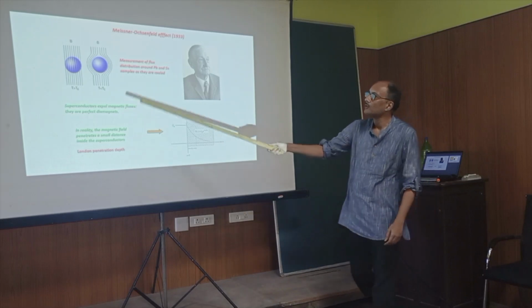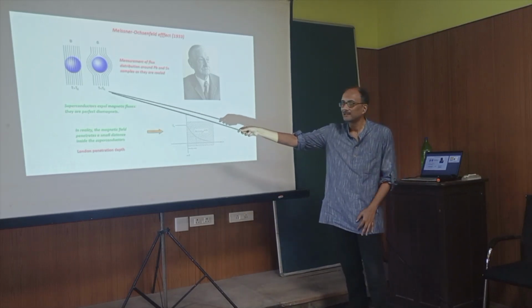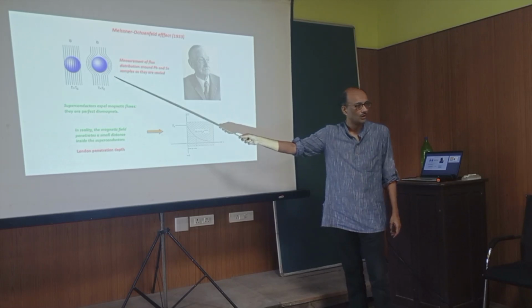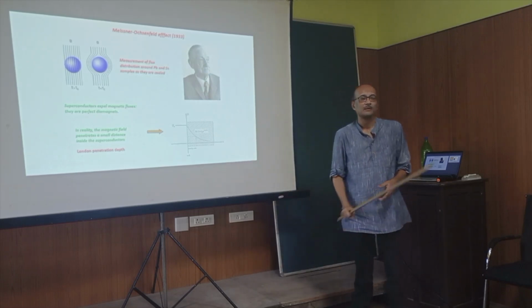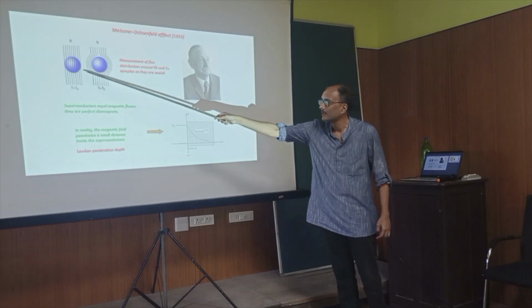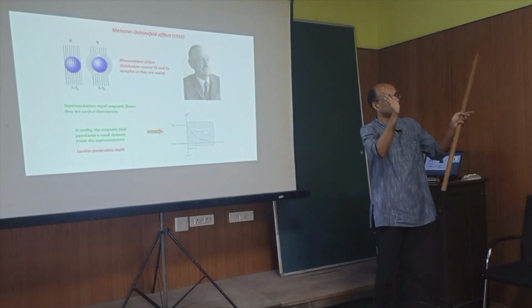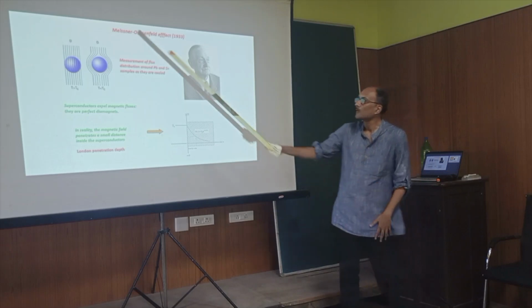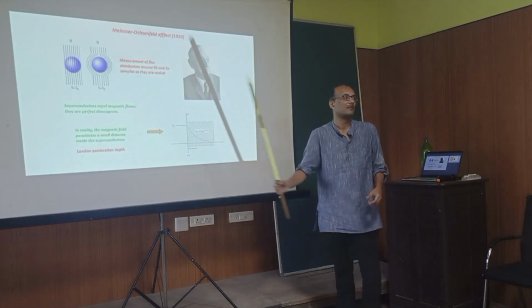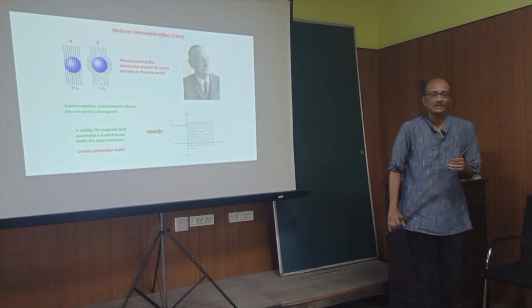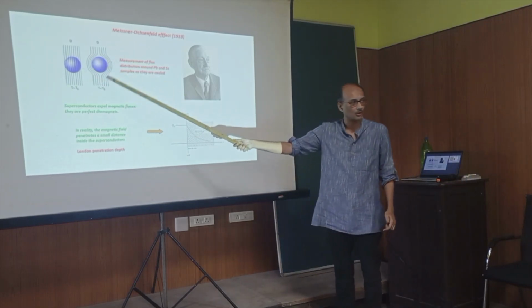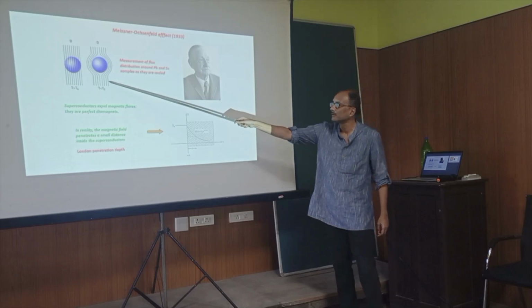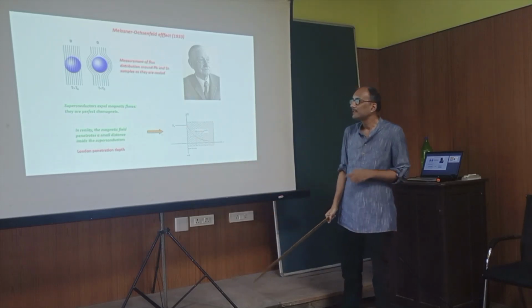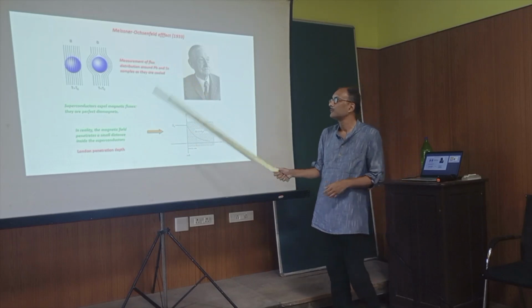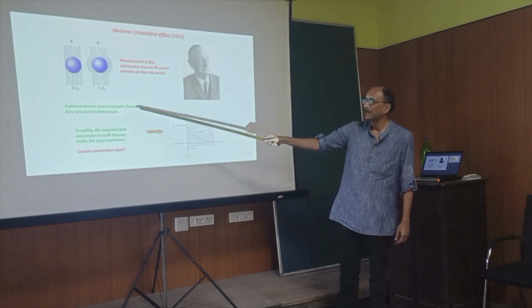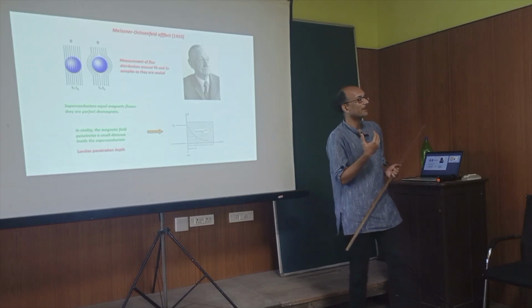And there, what he found is that once this temperature is so low that it goes into the superconducting state, the field lines around this sample get pushed to the outer plane. It's almost as if the sample repulses this flux line. Okay? So these are the magnetic flux lines, and there's a cartoon picture, of course. And then you see that it's just there. So this effect led him to conclude that superconductors expel magnetic fluxes, and in other words, they are perfect diamagnets.